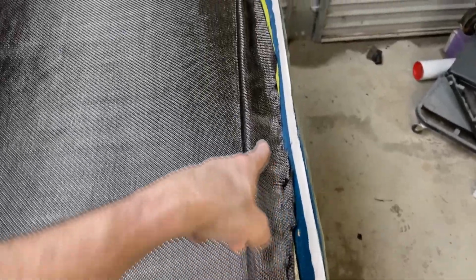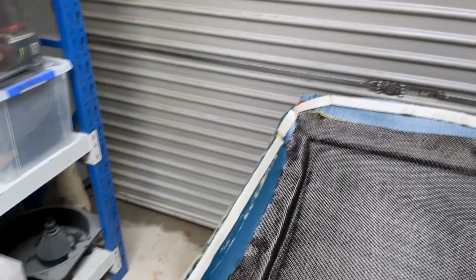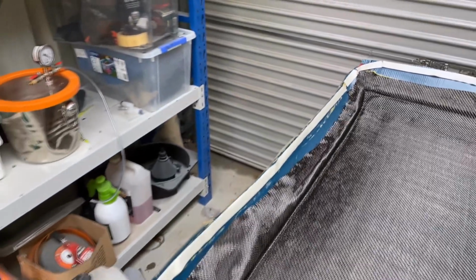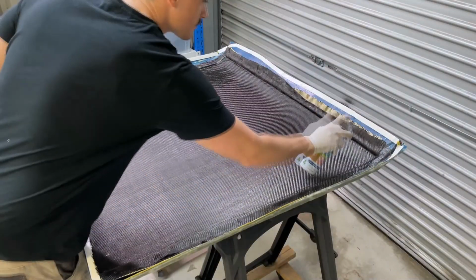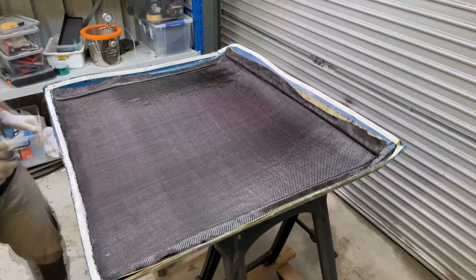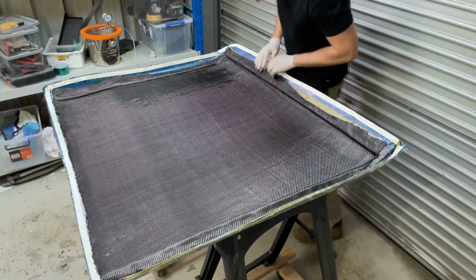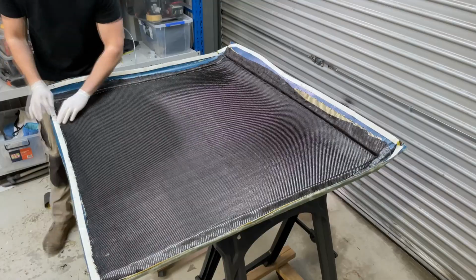So what I'm going to do is just put some spray glue all around the edges, and I think that will help glue down any of the fraying edges and probably prevent that from happening. Now, before making this piece, I've made probably 10 to 15 carbon fibre pieces, and honestly the majority of them have been failures because I failed to get a good vacuum over the system. So that's why I'm really spending this extra time to minimise the risk of getting any vacuum leaks as far as possible.